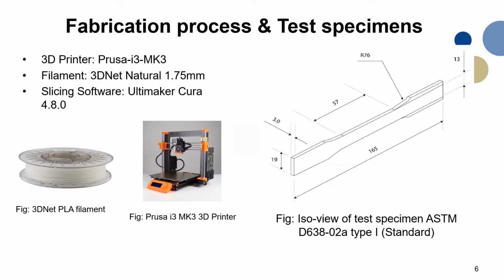For the fabrication process and test measurements, for the printer we have used a Prusa i3 MK3, and for the filament, we chose 3D net. The color is natural, and the diameter of the filament is 1.75. For the slicing software, we used Ultimaker Cura 4.8.0 to slice the specimen. So these are all the dimensions for the standardized specimen. It has a thickness of 3 millimeters. In this case, we treated this one as 100% scale, and we scaled down to 50% as well as 30% to make a comparison for the scale effect.